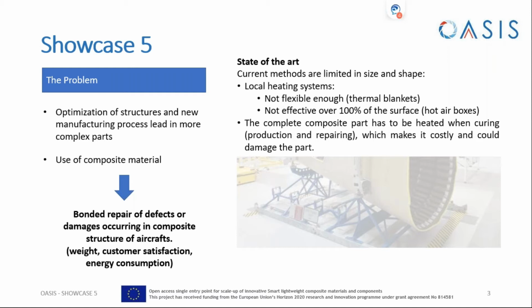And if we use the complete composite part curing, we have to take care, because it could damage the part, and it also makes the repair costly, because we have to heat up the complete part instead of a small area.